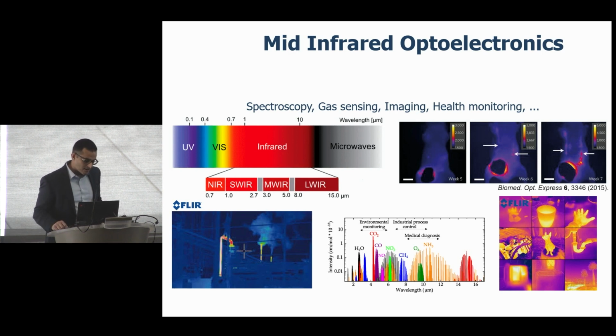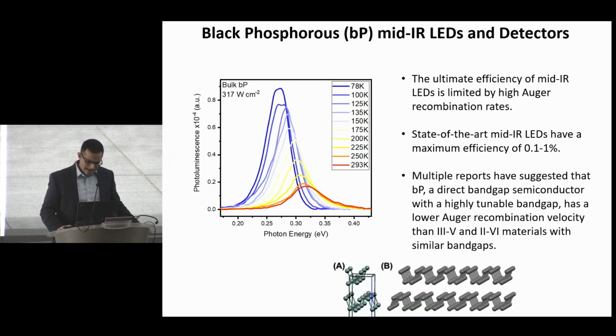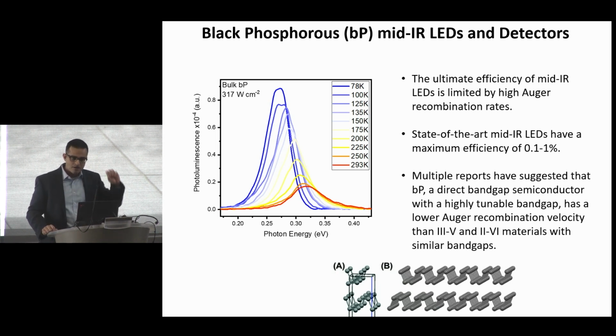If you can move to mid IR, you really open up a whole venue of capabilities, because most molecules have their fingerprints in the mid-IR regime. So you can start to look at chemical sensing. Now, a problem with mid-IR is that when the band gap of a material is very small, the material typically suffers from efficiencies. Specifically, if you have a material in the mid-IR with the band gap of, let's say, 0.3 electron volt, the maximum efficiency that you can get from that material for light emission is about 0.1, at best 1%. Those are the commercial, state-of-the-art commercial LEDs in mid-IR. $300, tiny LED, 0.1 to 1% efficient.